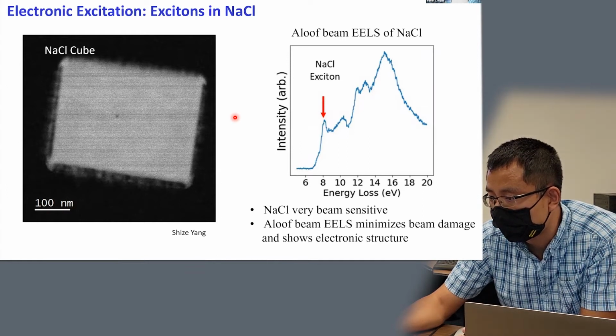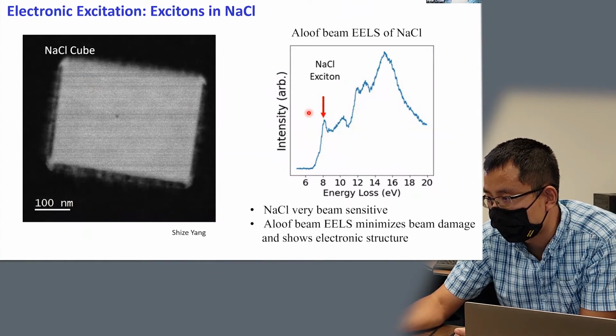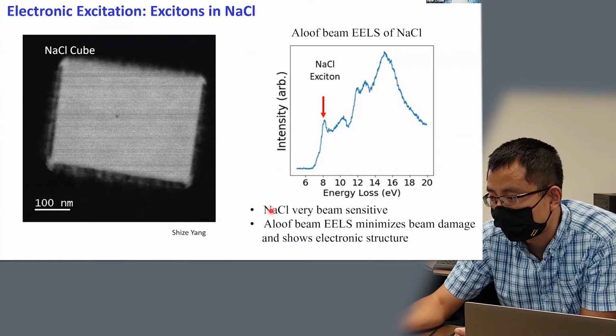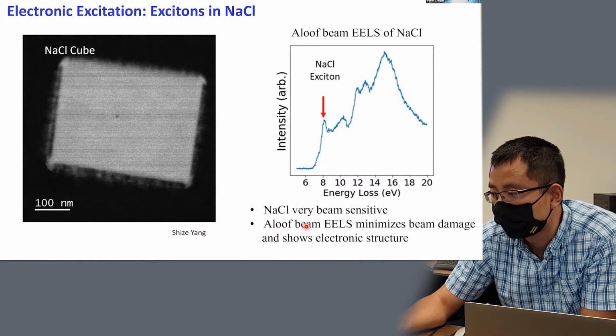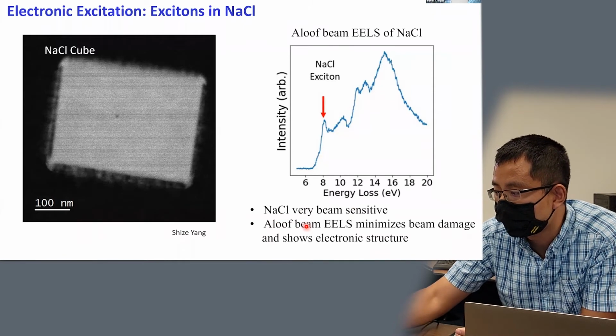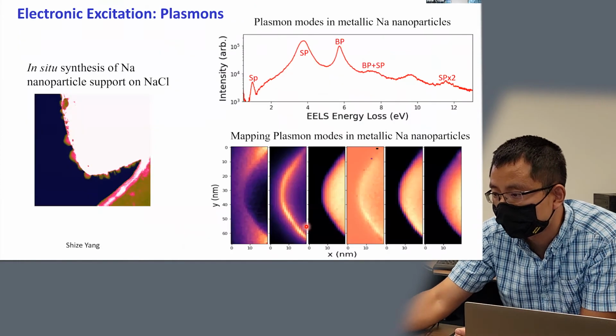And on the left is an ADF image showing a sodium chloride cube. And we can use aloof beam EELS to measure the exciton signal from the cube. You know that sodium chloride is very beam sensitive, and the aloof technique provides a unique way to reduce beam damage and probe electronic structure.